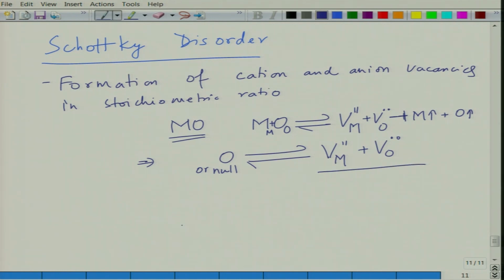What this means is that both metal and oxygen have to leave the system. So this generally doesn't happen in the interior of the system, it happens at the surface. That is why these defects are usually found there, because the metals and oxygen have to diffuse out of the system, and this diffusion takes energy and it is more plausible at the surface than in the interior. So these defects generally form at the